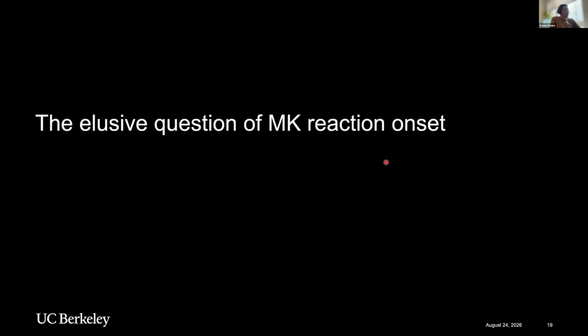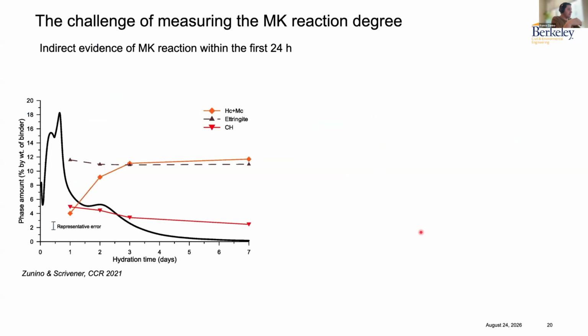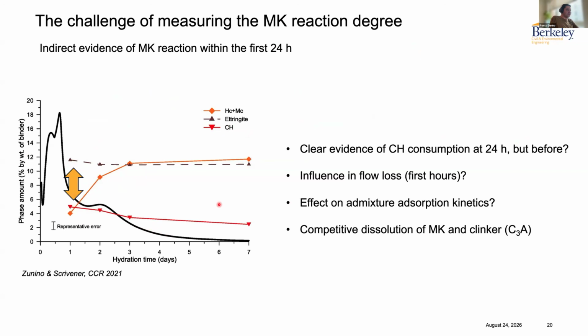The last point of my seminar for this morning is some thoughts on what I call the elusive question of the metakaolin reaction onset. And we have had evidence for a while now, this paper is from 2021, that metakaolin is very reactive, right? So we can record using classical experimental techniques calcium hydroxide consumption as early as 24 hours. But then the question is, how much earlier than 24 hours did that reaction actually become significant, and can we assign metakaolin a role in things like sulfate requirement or superplasticizer consumption and demand for workability given an accelerated pozzolanic reaction?